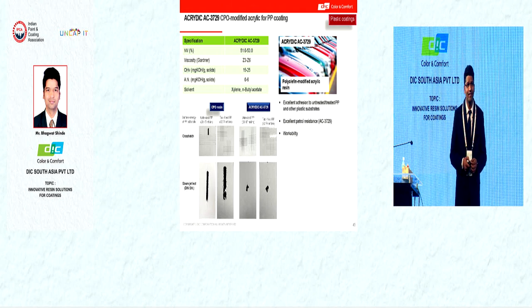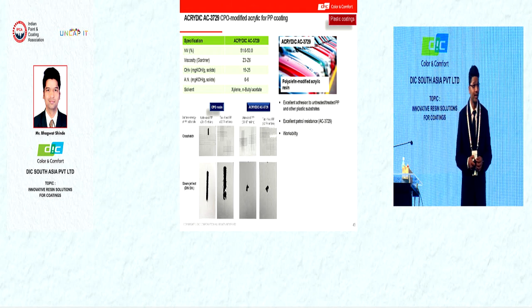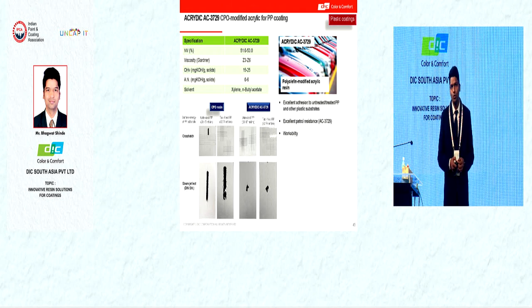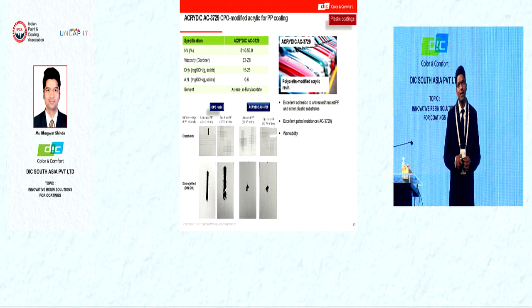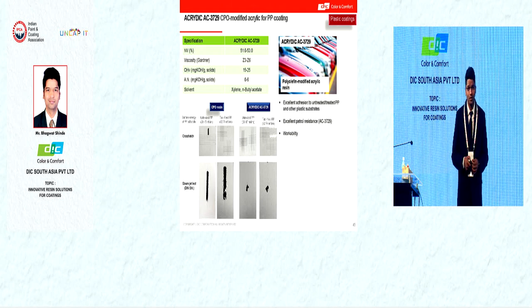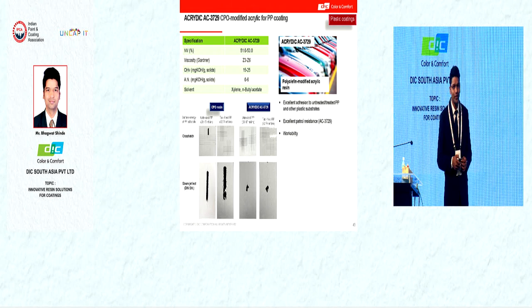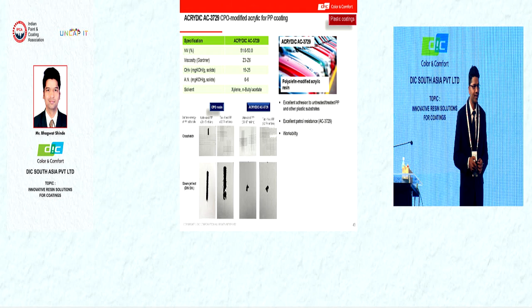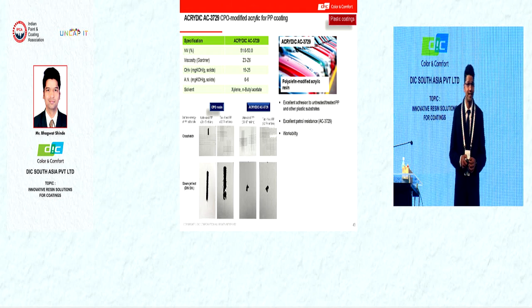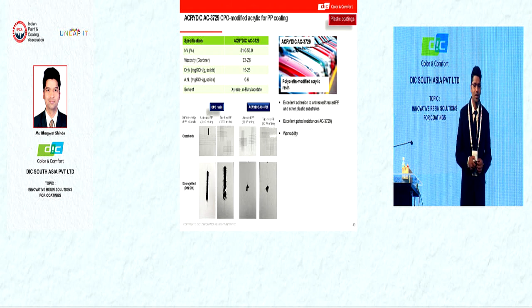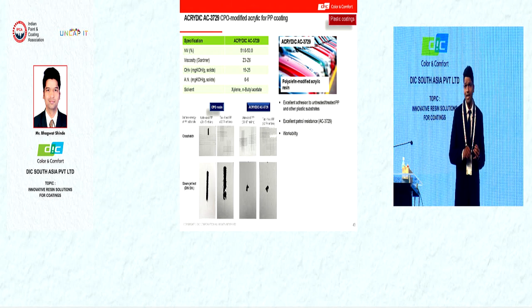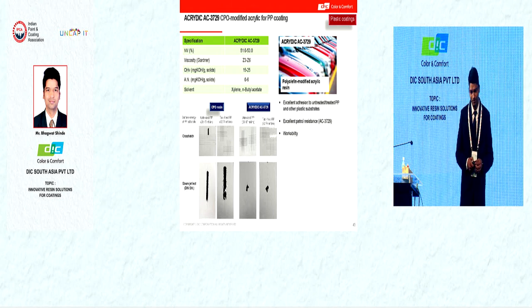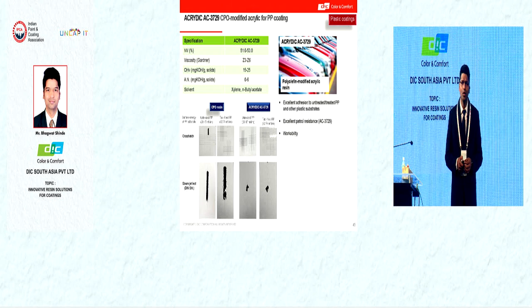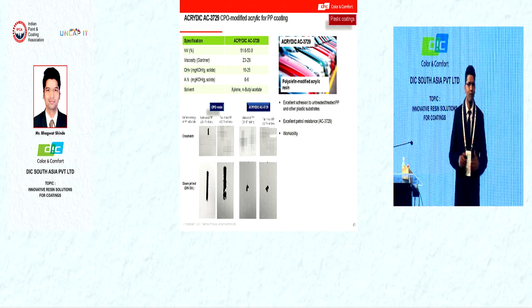But this CPO resin has some drawbacks, like workability. This CPO is in solid form, so we need to dilute it before the application, and it increases the time. Also, another drawback is the high cost of that product. So people are looking for an alternative to CPO resin. So we have CPO modified resins like 3729, 3696, and CL408. We have three products. You can use any substrate like talc-filled PP, pure PP, and other PP. It shows good adhesion. You have to apply 5 to 10 micron DFT and apply the top coats or a three-layer system, whatever you want, and it gets the adhesion.